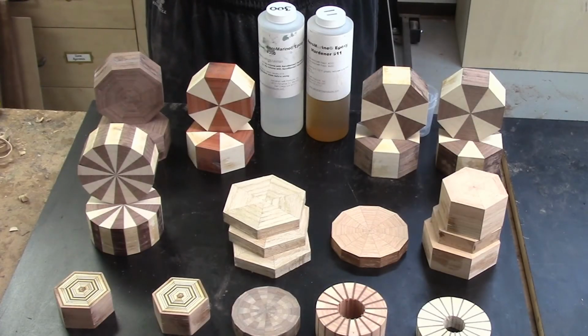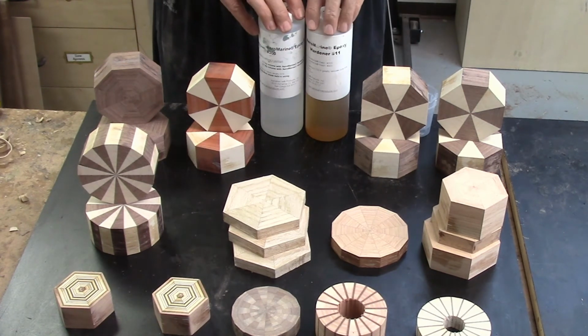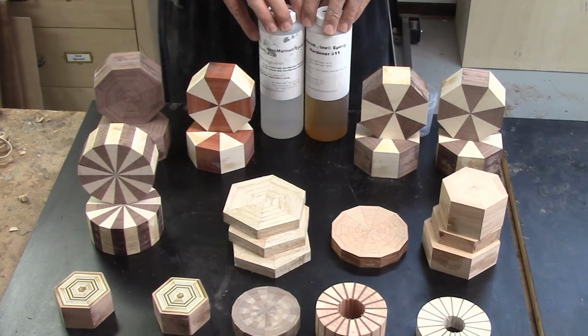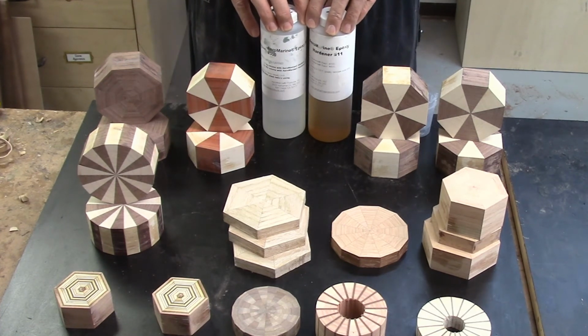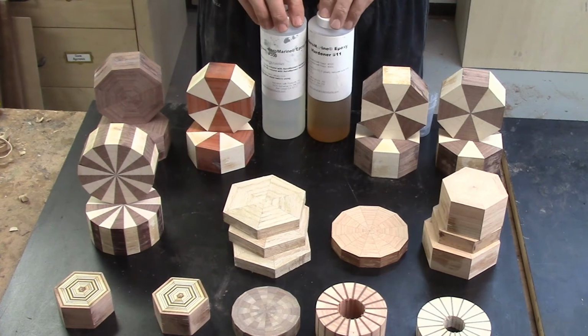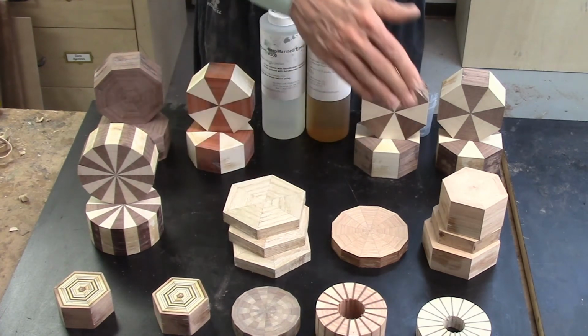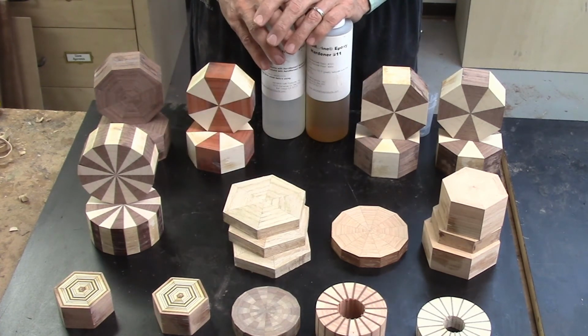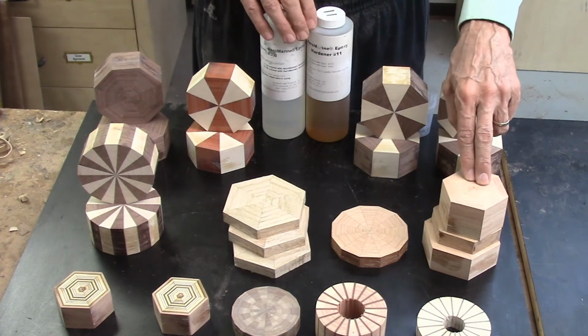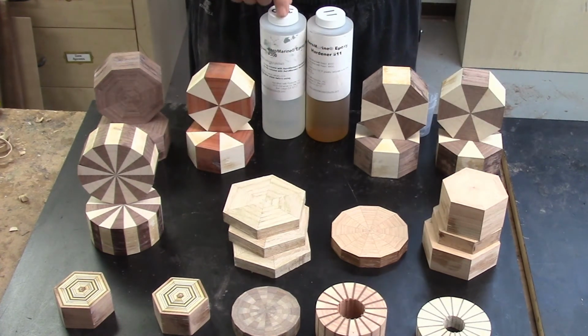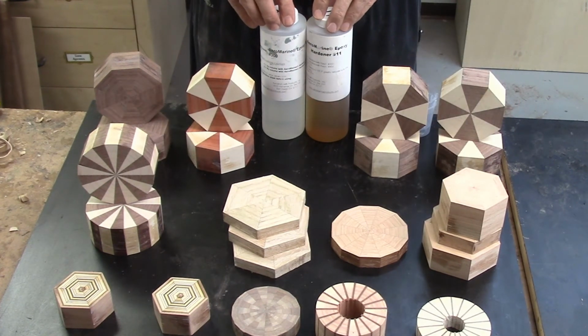In general, I'm quite happy with the results I received using the epoxy resin for gluing up my segmented rings. I tried both the thin epoxy resin and the thicker. I'm going to make the thicker resin my standard going forward. I think the thicker resin works a little bit better. So that'll be our standard resin going forward. These are just some of the mini discs I made using the epoxy resin. A few of these were made with a thinner resin, but most of these were made with a thicker resin. In general, I'm quite happy.